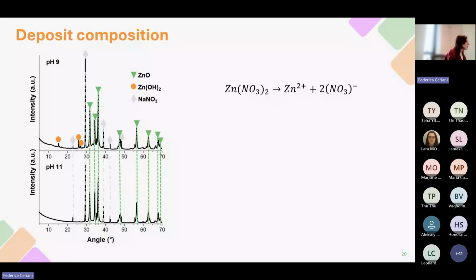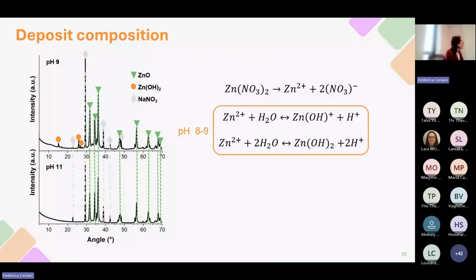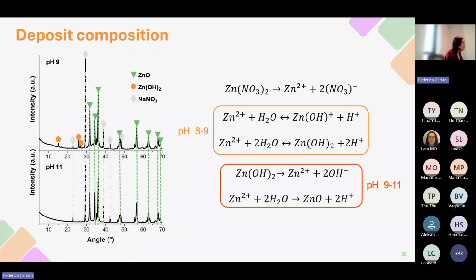In order to understand this difference, it is useful to analyze the reactions taking place within the sealing bath. First of all, of course, there is the dissociation of zinc nitrate into zinc and nitrate ions. Then, when the pH is adjusted and reaches value ranging between 8 and 9, zinc ions react, forming zinc hydroxide. But if the pH further increases, reaching value between 9 and 11, zinc hydroxide is almost completely converted into zinc oxide. This explains not only the difference between the two compositions observed in the diffractograms, but also the different morphologies observed for the sealed samples.